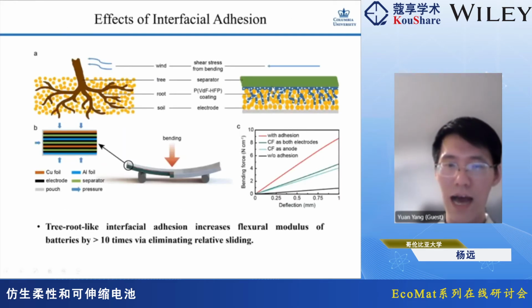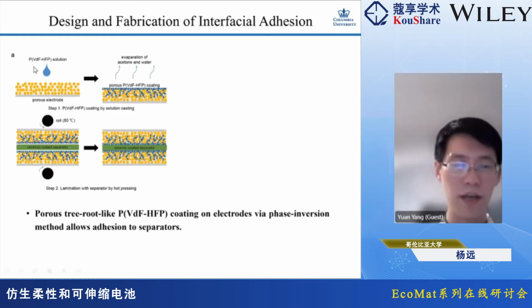The reason is that now all layers are laminated together, like we laminate all pages in a book together, so the book becomes like a brick and is pretty strong. To do it, we dissolve PVDF-HFP. This is a polymer the battery field should be pretty familiar with. We put it onto the electrode surface, and by tuning the viscosity and the porosity of this film, we can let it go deeply into the electrode, and then use a hot roll press to integrate the separator together with the active particles, and finally.